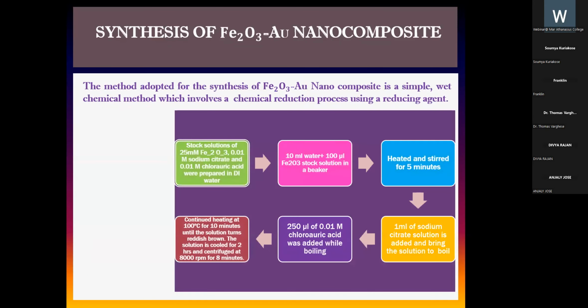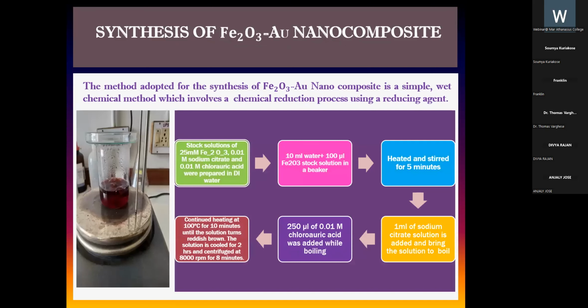So we have synthesized a nanofluid of iron oxide and gold by a simple wet chemical method, where iron oxide, chloroauric acid, and trisodium citrate were used to form a nanocomposite of Fe2O3 Au. The synthesis technique is depicted in the figure, which explains the chemical reduction process to form the nanofluid composite. After synthesizing, we have confirmed the formation of nanocomposite through various optical, morphological, elemental, and structural characterization, of which a few are to be discussed here.